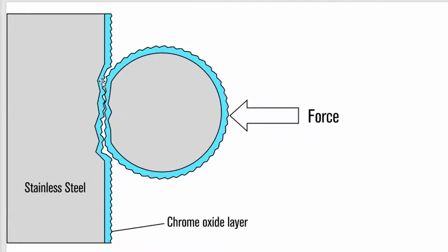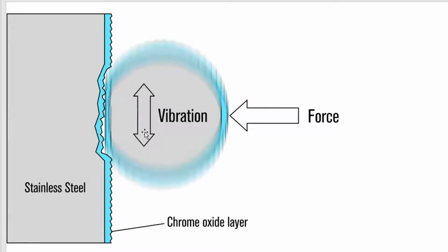Okay, so in this case, we've had rubbing. If you'll notice something else, because this is starting to wear away at each other, now you will get a flat spot on this cylinder, and you will also get a flat spot on the corresponding contact surface. And you will see that on the parts when you inspect them. Now, what happens from here on? Well, there's probably still that same relative movement. It's not just going to go away once you've reformed the oxide layer. And what this means is this will start all over again.